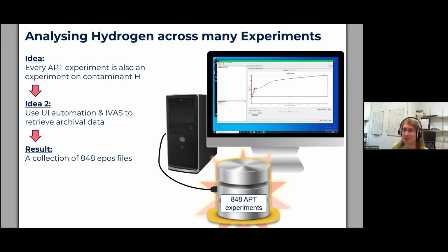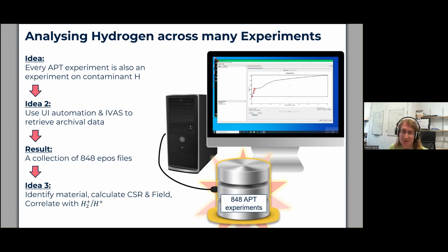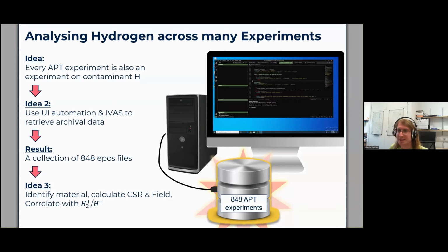The next two steps that we do to these data sets is, firstly, we identify the material. And once we know the materials, or at least once we know the main ions in there, we can calculate charge state ratios and electric fields. In addition to that, we can also calculate the hydrogen peak height ratio, so the counts of the H2+ ion divided by the counts of the H+ ion. And what this is doing is essentially condensing at least a good approximation for what the hydrogen spectrum looks like in a particular experiment into one single number that we can easily track across many experiments.